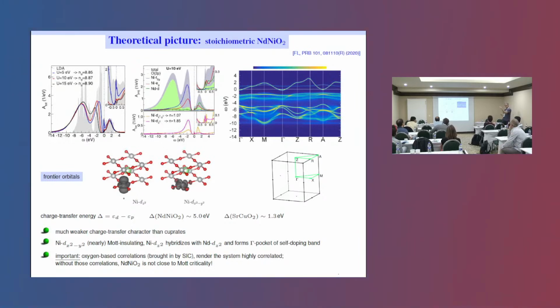However, it's quite different for the late transition metal oxides, where we have this kind of architecture with a direct hopping path across the oxygen in the eg system. Because you want to put holes in there, the hole has to jump somewhere. It likes it because of the Heisenberg principle, but it cannot easily jump to the oxygen as in cuprates and nickelates. So the transport will be blocked more easily in this nickelate. So the hole likes to go somewhere else, and what is there? As you have seen, the nickel d z-squared is closer. So that will be the story, but the bottom line is this simplistic kind of arguing that I just put forward.